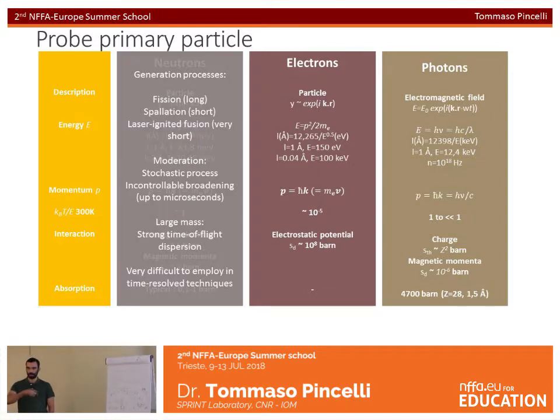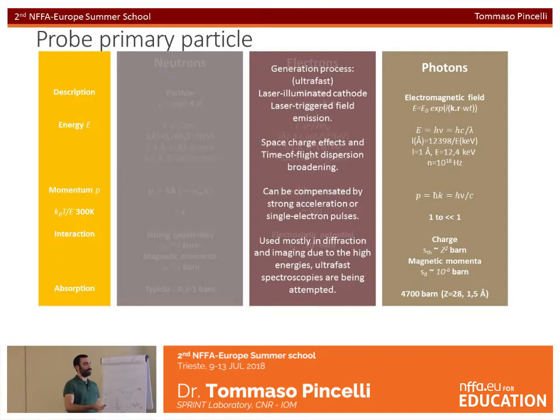And then we have also a strong time-of-flight dispersion due to the fact that they have mass. So they have a quadratic dispersion in time when they fly through the neutron guides. So these neutrons are very difficult to employ in time-resolved techniques. What about electrons instead? Well, they can be generated on ultrafast time scales. Electrons are produced from cathodes, and you can illuminate the cathode with a laser, so you can create a sharp pulse. Or you can produce field emission from a needle by triggering it again with the laser.